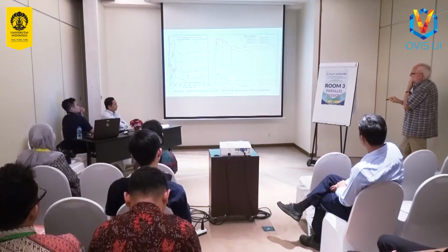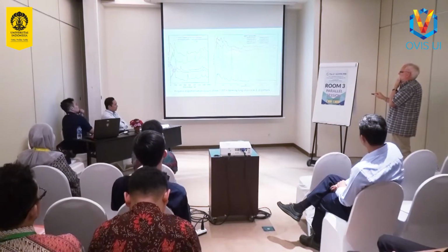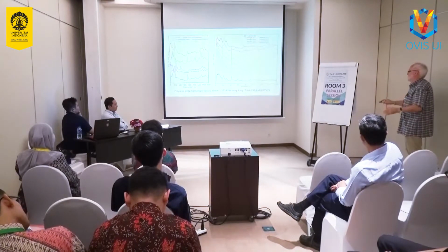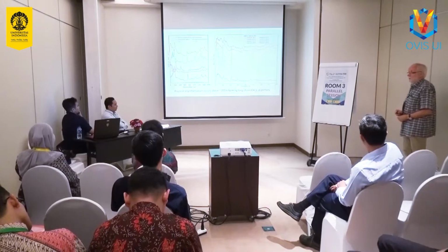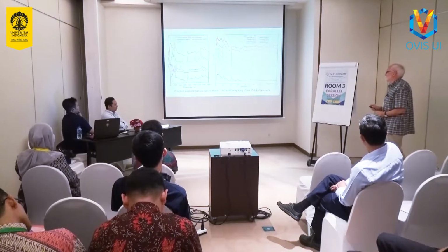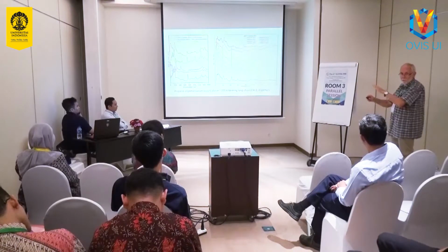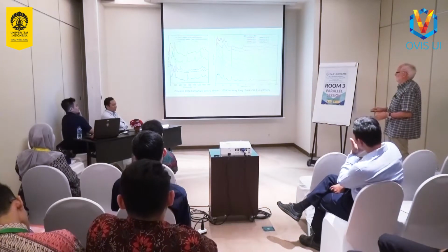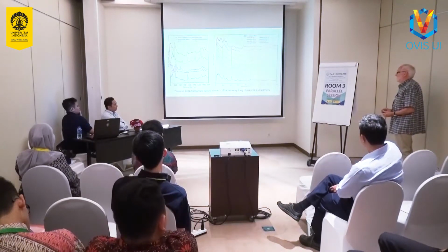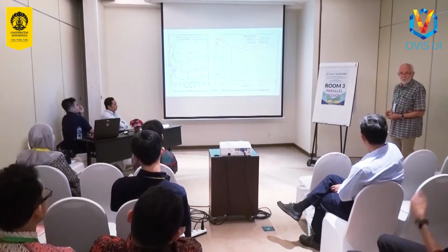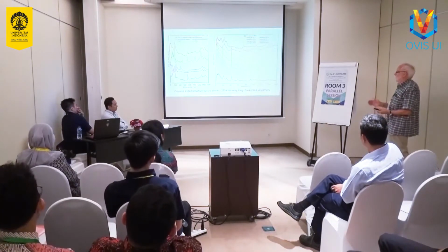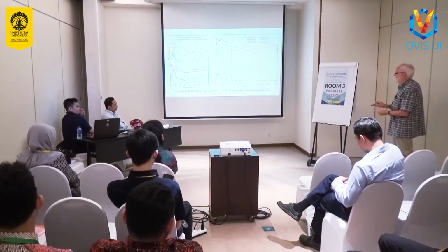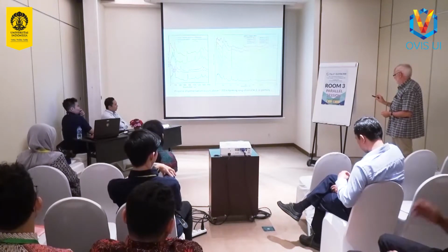So the conclusion we reach is that above about 255 Kelvin, propene is oligomerizing in the zeolite and forming long chain CH2 oligomers. And the vibrational spectrum of them is consistent with basically linear chains rather than highly branched ones. We do that by comparing the spectra of model compounds and also with some theoretical modeling. And 1-octene does the same thing. So at room temperature, the zeolite protons are active enough to be able to cause oligomerization of the olefin at room temperature.